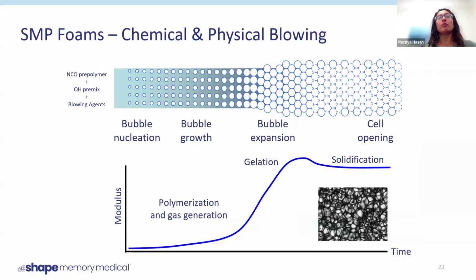So the gas blowing foam process occurs in several steps. After we have mixed our isocyanate and hydroxyl resins and some blowing agents, we see some initial bubble nucleation over time, and at this point, the material has pretty low modulus. It's not gelled at all. Over time, there's bubble growth, and we start to see the modulus rise a little bit. The catalyst will eventually kick in, while the blowing agents are also doing their job and causing more bubble expansion. So as the catalysts are kicking in, we start to see the modulus rise while there's more bubbles being formed. So the foam is actually rising at that point.